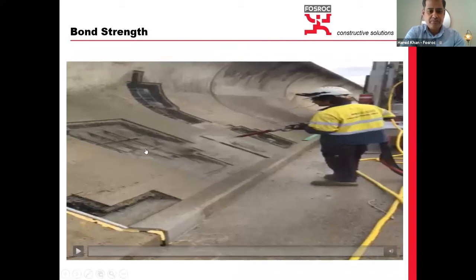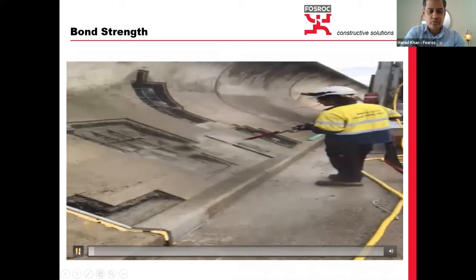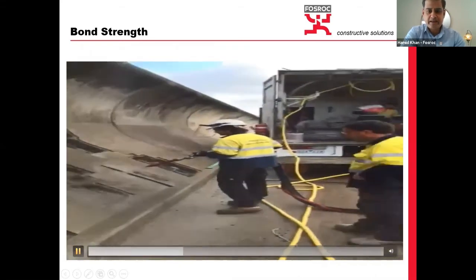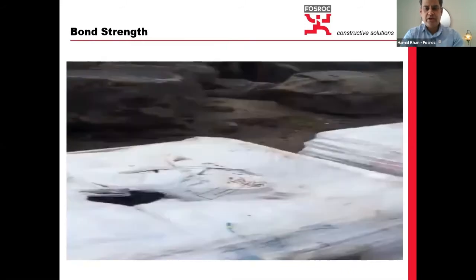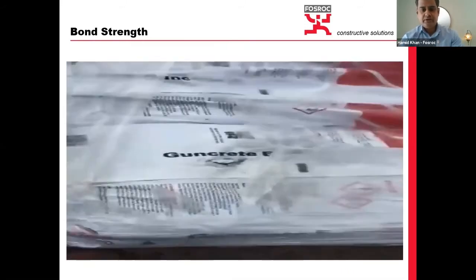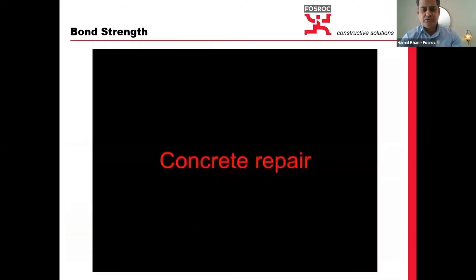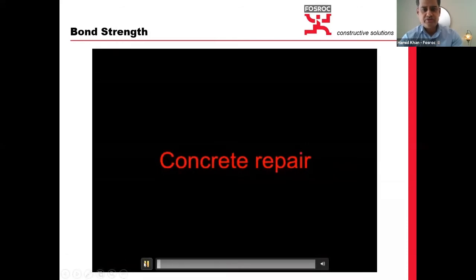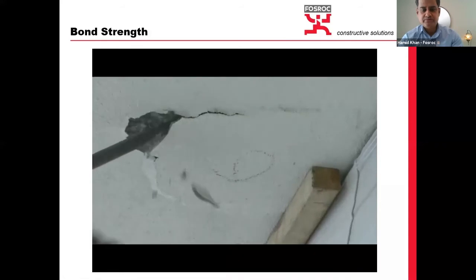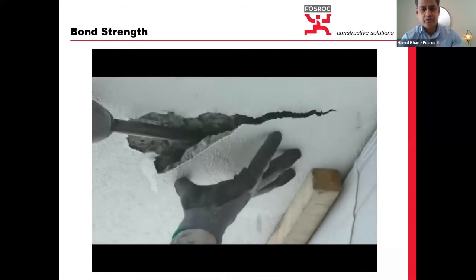When we have a proper saw cut and a geometric pattern for sprayed mortars, they already have a good profile. Let me see if it works. There are sprayed mortars that can be applied, and such surface preparation that you have seen in the previous slide would really provide a very good bond strength. So bond strength is not only about repair material. Let's have a look at this again, guys.